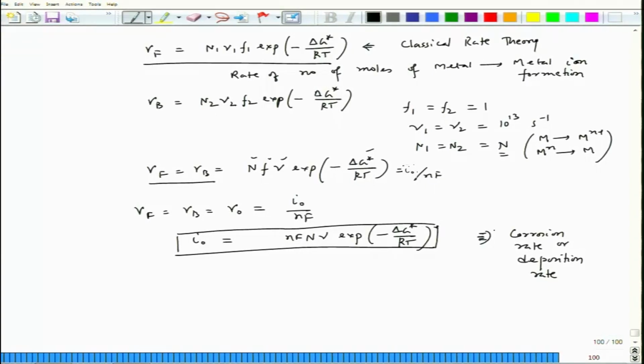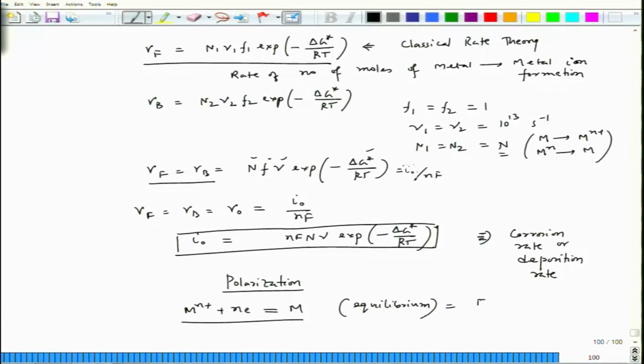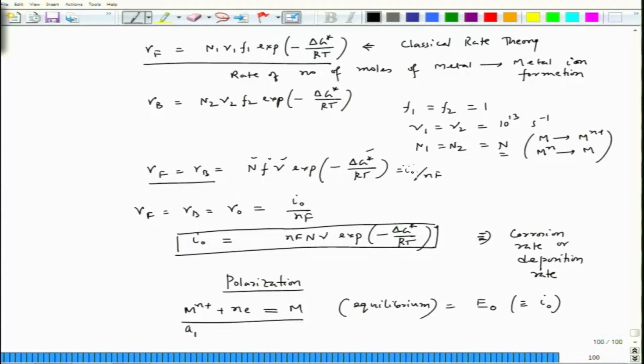This is not the same as corrosion rate, but it can be related to it. Now, we have used one term called polarization. When we talk about polarization, it means that it is a shift from the stable value. Now, we see that when M n plus plus n e M is reaching equilibrium, we have a potential, which is of course giving a situation of I 0, which is exchange current density, and if we have maintained standard value, it would